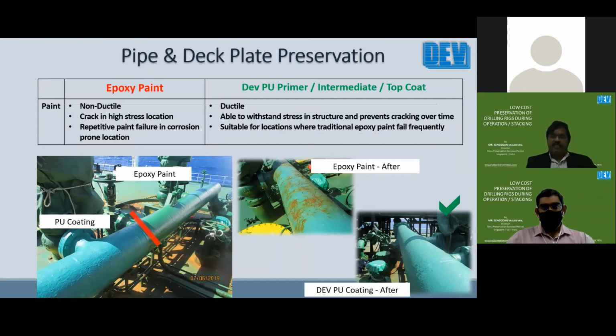And this is a very successful example showing the difference between an epoxy paint and the PU coating product we have discussed. The epoxy and PU were applied at the same time, and later during service, when the epoxy failed miserably like this and corrosion started on the piping, the PU coating continued to perform like this. We recommend this be applied in locations where the epoxy paint film fails frequently. If the epoxy is providing service, say you apply it and it stays there for 5 years with no problem, then you can leave it as such. But wherever there is a failure of the epoxy leading to corrosion, we can locally use this PU coating, which is compatible with the existing epoxy. That way we don't have to completely remove the epoxy in all areas to replace it with the PU coating. It can be locally repaired as a repair solution.